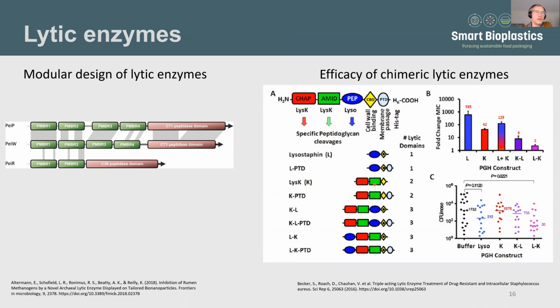So you take different domains, put them together, change the orientation, change the number, very much like synthetic biology. And then he looked at how active are those? And if you can see here, it describes the fold change in minimal inhibitor concentration. You can actually achieve almost 1,000-fold increase in activity and lack of resistance forming by changing and playing with the orientation and order of those functional domains, which means